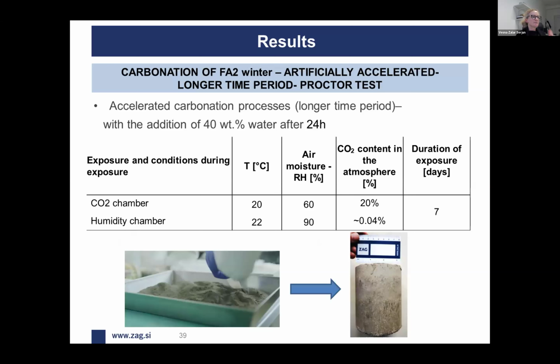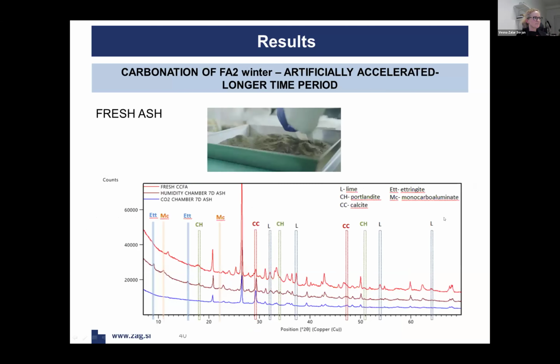defined to check the longer time periods and to use the carbonated sample of ash for the preparation of geotechnical composites, and then to follow the mineralogy of those geotechnical composites. We again use CO₂ chamber and humidity chamber, with higher moisture content and lower CO₂ concentration in the humidity chamber, and the CO₂ chamber just the opposite, and duration of exposure was 7 days.